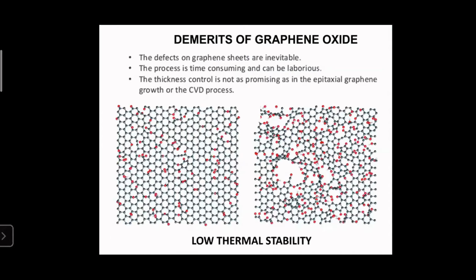Another demerit of graphene oxide is that there are always defects on the graphene sheets produced via graphene oxide assisted methods. The process is time consuming and laborious, and sometimes thickness control is not possible. Still, we sometimes get monolayer graphene, but from my point of view, one of the major limitations of graphene oxide is its low thermal stability, due to the presence of various functionalities as well as defects and holes on the graphene sheets.